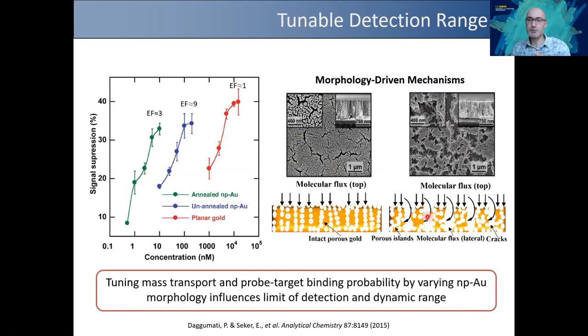But if you have this cracked morphology, you have these isolated porous islands where you can have transport and permeation from the sides as well, which increases the probability of capture further. So we think that this is really a morphology-driven mechanism.